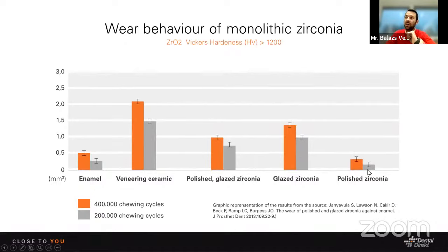Just a glazed crown and just a polished crown. And what you see here is basically the most effective and the most gentle way for the natural teeth, for the antagonist, when you have your monolithic crowns polished. It means with the polishing technique, we can reach even better abrasion properties for a zirconia crown, like the natural teeth. That abrasion will not damage our natural teeth. So this is the best technique you can do for a zirconia crown.